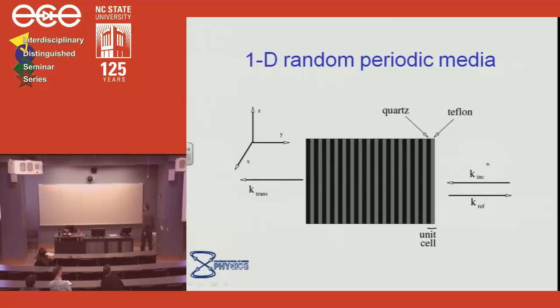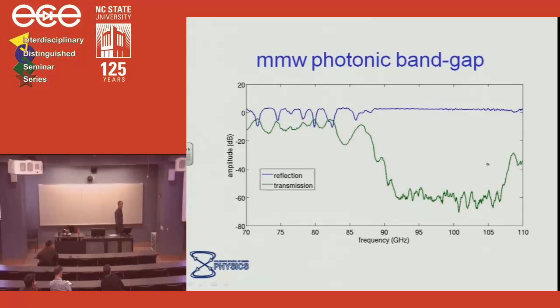And so whenever you have a lattice, a periodic system like this, the first thing you should expect to happen is you should expect to see a band gap. And so maybe you probably haven't taken solid state physics, but a band gap occurs between frequencies where you can just fit a single wavelength in between the two different lattice spacings. And so in this case, you can predict that the band gap is going to be at 90 gigahertz. And what you're seeing here is the reflection coefficient, and this is the transmission coefficient. And so below the band gap frequency, this is essentially the Fabry-Perot response, these oscillations here. But when you hit the band gap frequency, pow, the thing becomes a perfect reflector.